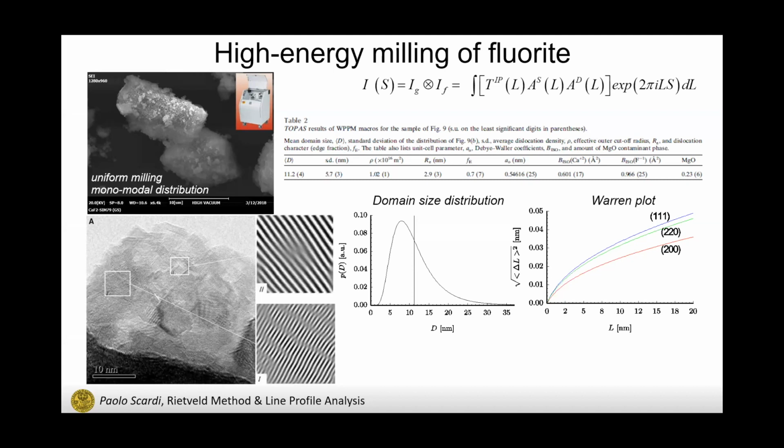And this is an intrinsic property of many binary compounds, which have the H00 direction, which is, let's say, the stiff direction, elastically speaking, whereas the HHH is the compliant direction, which is quite opposite to most cubic metals. The Warren plot is preferable because the method I have just shown you, which is based on the Krivoglaz-Wilkens theory, has a tendency to overestimate the